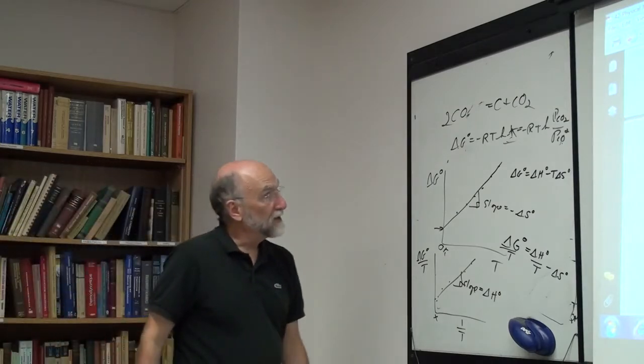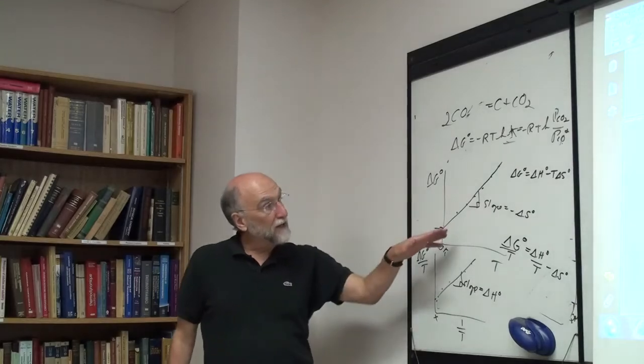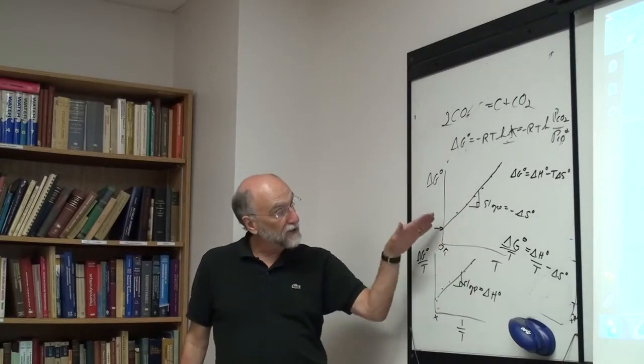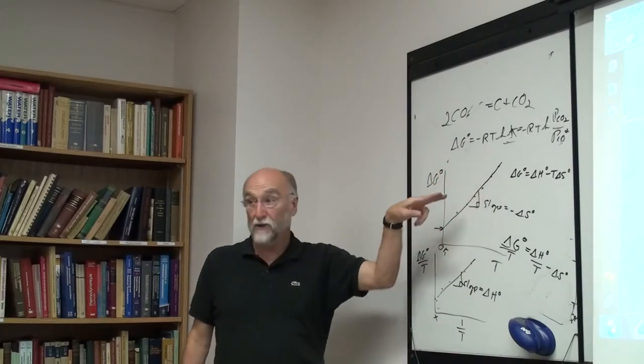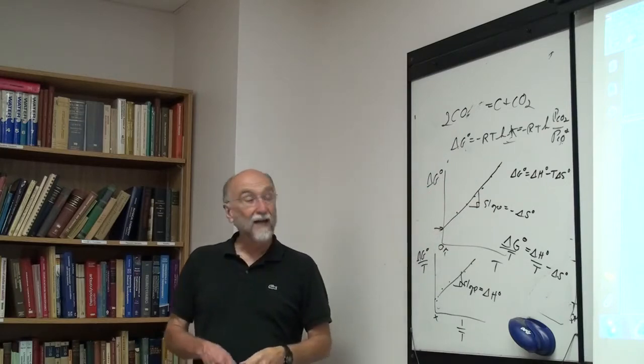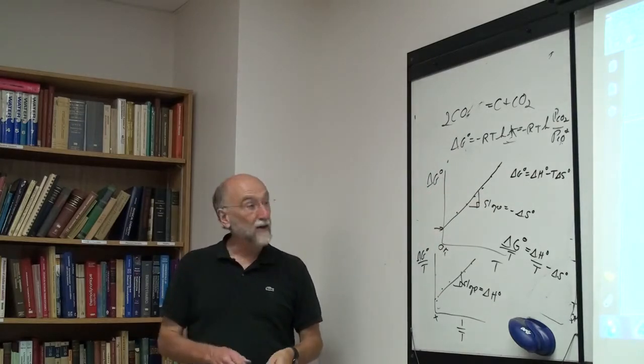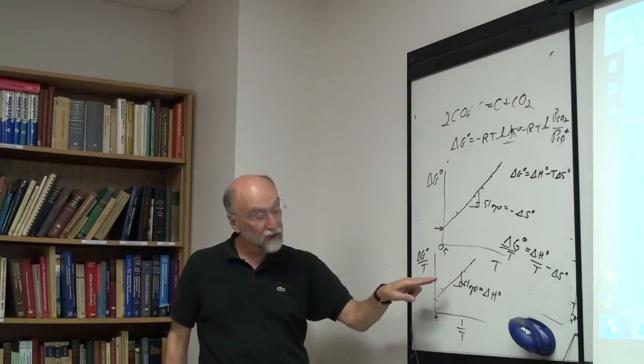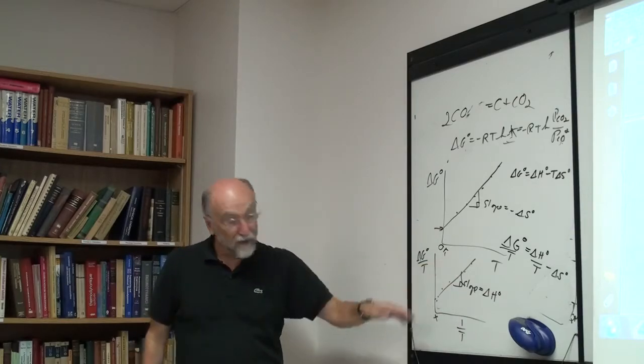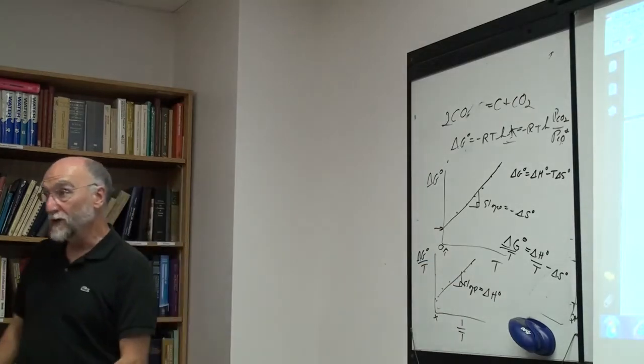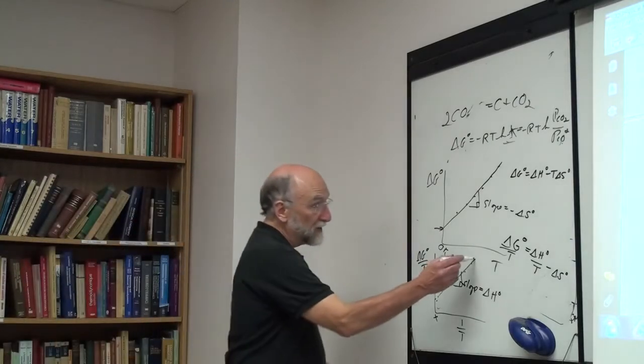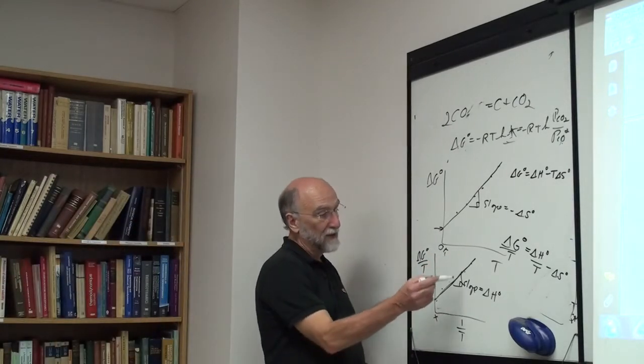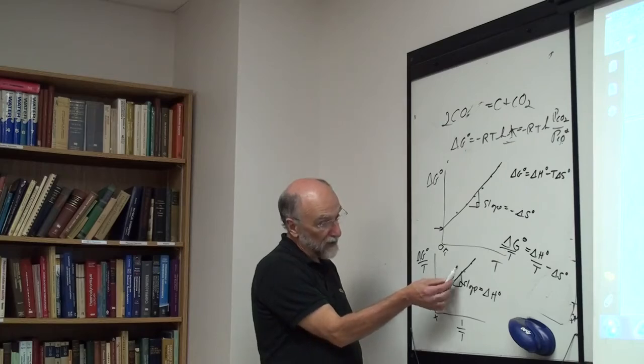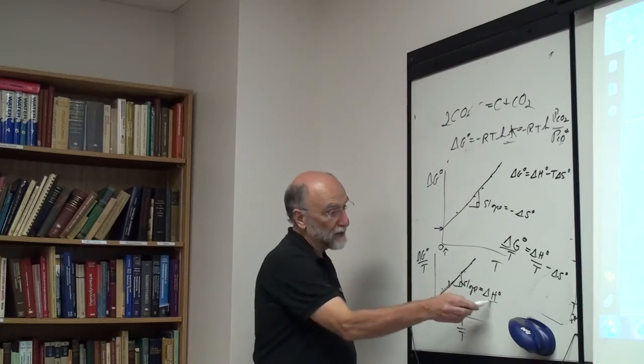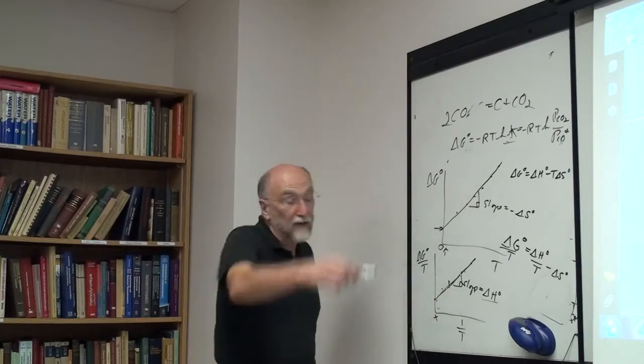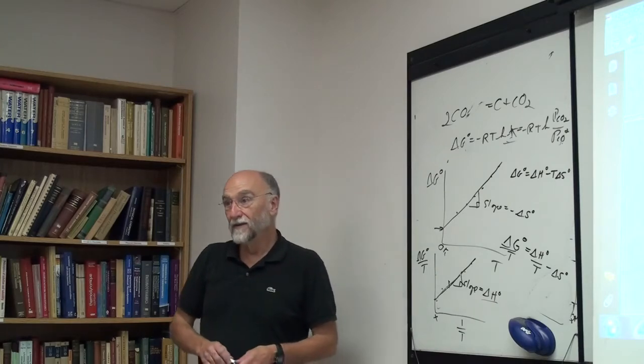Clearly, experimentally, this has some problems because this is a derived quantity. You're not measuring directly S or H, it's the slope of another, it's the difference between two measurements, which is always less accurate than measuring something directly. You're not directly measuring H, you're measuring the change in G, so you have to measure the difference between two measurements. Now it all depends on the temperature range. If your temperature range is very small, then obviously a very slight error can cause a big error in delta H. If you've got a big long temperature range, then things are a lot better.